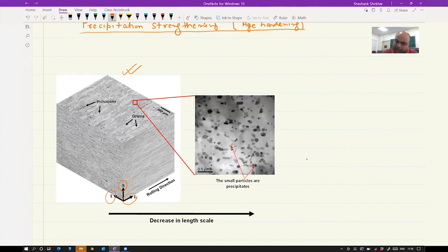We will not go into that much detail about all the series of aluminum alloys. What you see typically here, if you look in an optical microscope, is grains. So you can see all these grains here. Then you can also observe inclusions. These dark particles, we call inclusions. In 7075 aluminum alloys, these inclusions are silicon rich or iron rich. We don't want them, but they will be present in the aluminum alloy. But what I wanted to point out here is the scale bar. This is 300 micrometers.